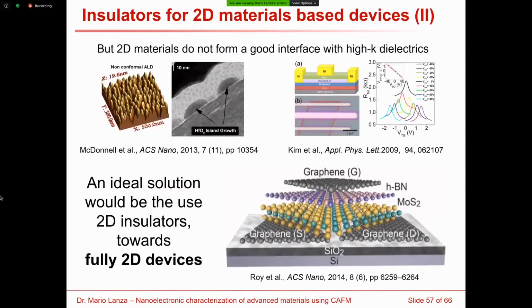So in order to avoid this problem, in our group, the first strategy that we thought of is let's try to go over to fully two-dimensional structures. That means using a two-dimensional dielectric. And among the family of two-dimensional materials, the one that has better dielectric properties, the one that has higher band gap, is hexagonal boron nitride. So this is the material that we started to analyze.